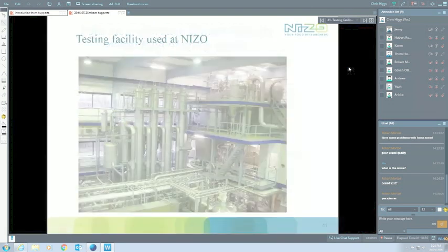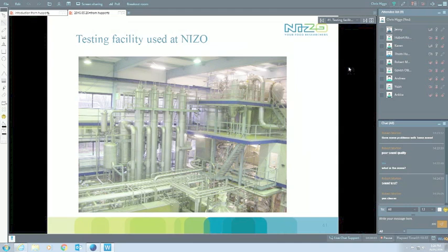So just to run you through it for a second, what we did here basically is use our dryer in the pilot plant. A nice multi-stage dryer, about 250 kg water evaporation per hour, so not full commercial scale, but still decent scale to give you very realistic insights, with the evaporator of course there as well.